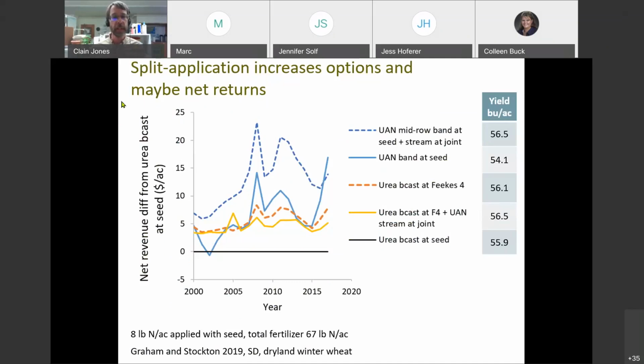This is some work done in South Dakota, in a fairly similar rainfall environment to Montana, where they looked at 5 different timings and placements of nitrogen. Their control was urea broadcast at seeding, and they conducted this study for a very long time and kept repeating the study, almost 17 years. Here on the vertical axis, I plot net revenue difference from urea broadcast at seeding, which is shown here as the black line. Urea broadcast at growth stage Feekes 4, plus some more nitrogen streamed on at jointing, did a little better. Urea broadcast at the Feekes 4 stage did slightly better.